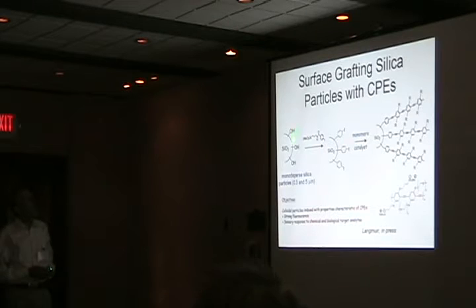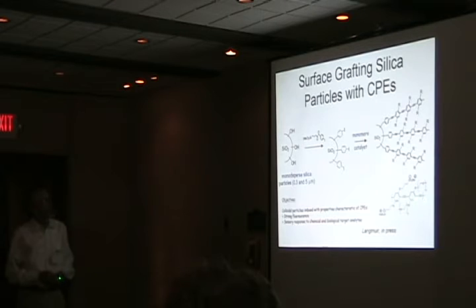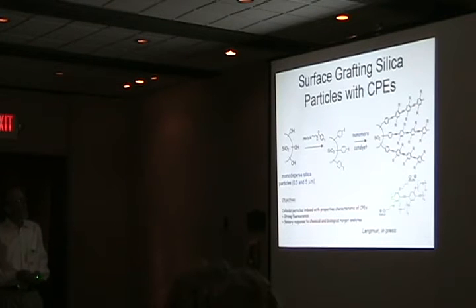And this involves actually growing polymers, these polyphenylene ethynylene polymers, directly onto glass or silica particles. Essentially what we do is we react the silica particles with an iodobenzene unit, and then we add the monomers that will give us a polymer. And here's the polymer we normally form. One of the monomers is a diiodobenzene derivative, and the other is a diethynylbenzene derivative. So these give you this polymer where you have alternating phenylene ethynylene units.